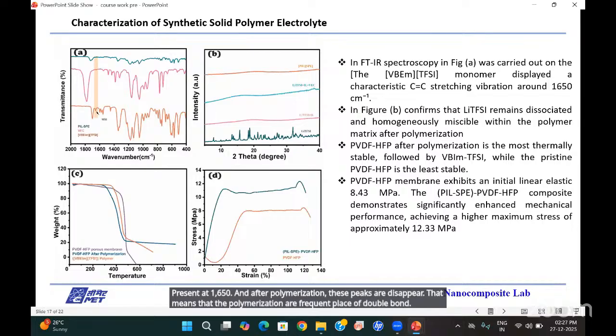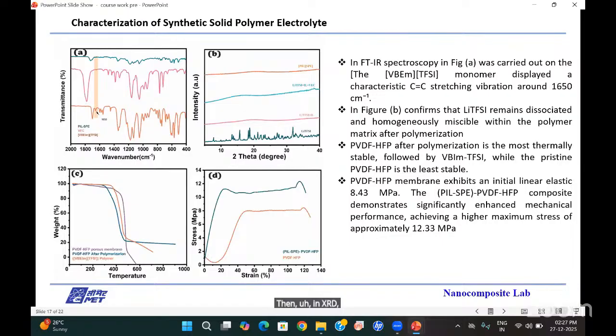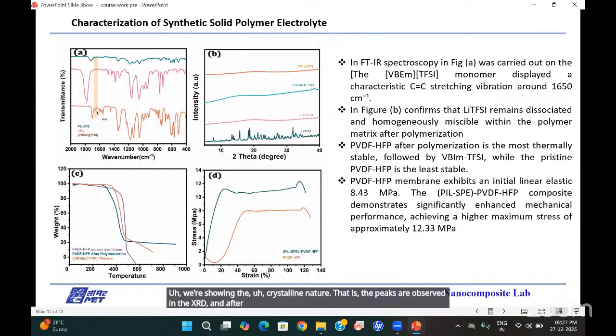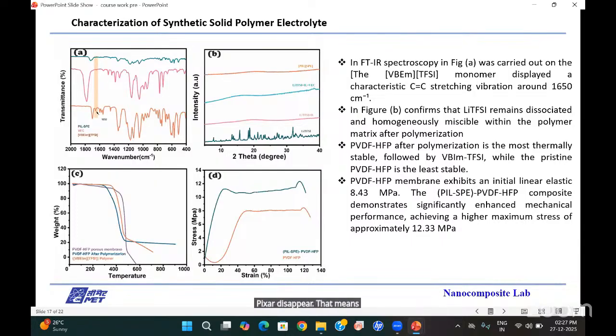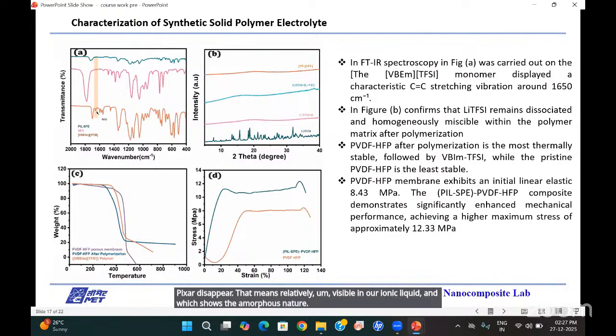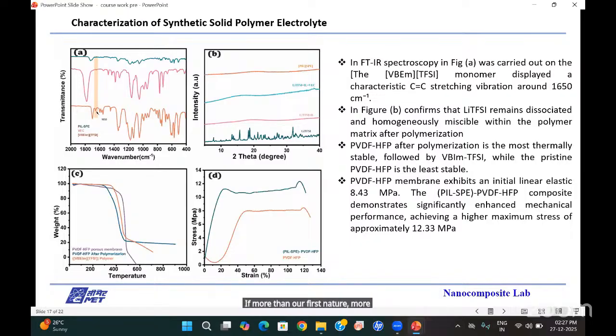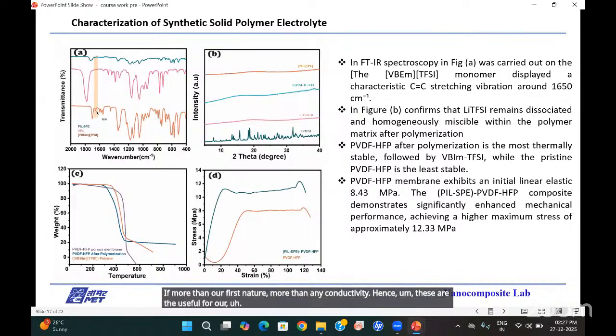Then in XRD, we show the crystalline nature of the LiTFSI, with peaks observed in the XRD. And after we mix the LiTFSI in our ionic liquid, these peaks disappear. That means LiTFSI is fully miscible in our ionic liquid, which shows the amorphous nature. The more amorphous the nature, the more the ionic conductivity. Hence, this is useful for our battery fabrication.